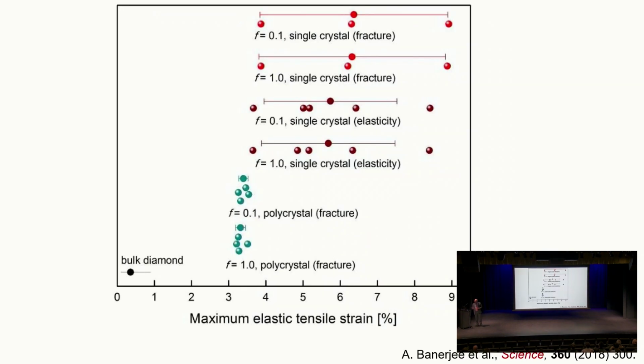So we summarized all of this in this picture. So what is plotted here is the maximum elastic tensile strain until failure. And F denotes the friction coefficient. So it's either 0.1 or 1.0. You have single crystal, when it fractures. When you have just elasticity, it means we went all the way and came back, and it did not fracture, but that was the maximum strain we were able to obtain. So we did multiple specimens, multiple videos. So the point of the story here is that you can get a strain as high as 8 to 9% maximum in tension in diamond at room temperature at the nanoscale.